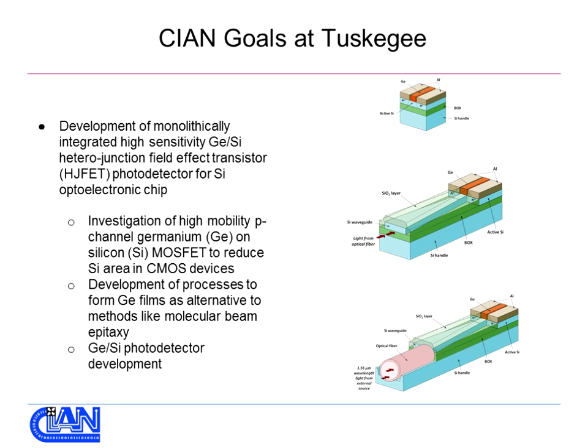However, in order to achieve this goal, we have sort of mini goals. And in general, we'd like to investigate the high mobility p-channel germanium on silicon MOSFET to reduce the area of silicon in the CMOS devices. Of course, this is a necessary part more toward the transistor than the waveguide. Also, we'd like to develop the processes to form germanium films. Specifically, we'd like to explore how much work we can do with sputtering as an alternative to molecular beam epitaxy. Because if we believe there's a lot of potential in sputtering, and if we can show that we can fabricate devices using this process, then we can significantly change the amount of money spent in fabrication. Also, a germanium silicon photodetector development in general, obviously for the main goal of this device, that's an essential part.